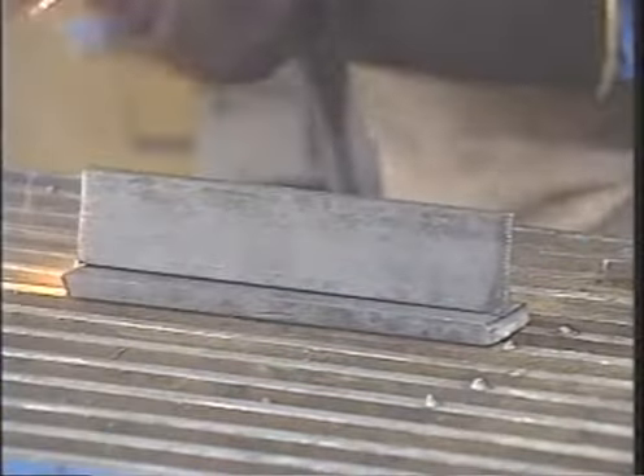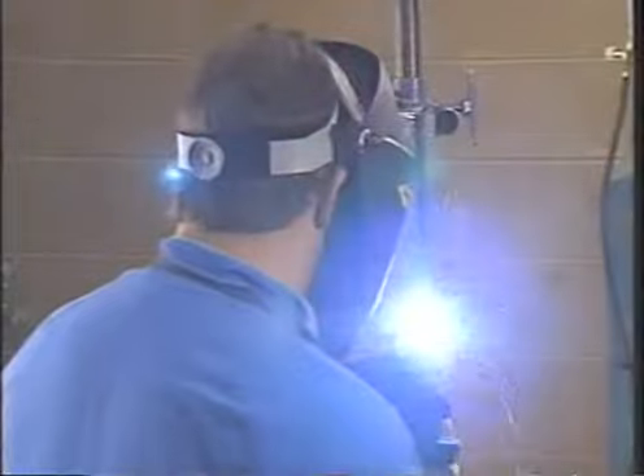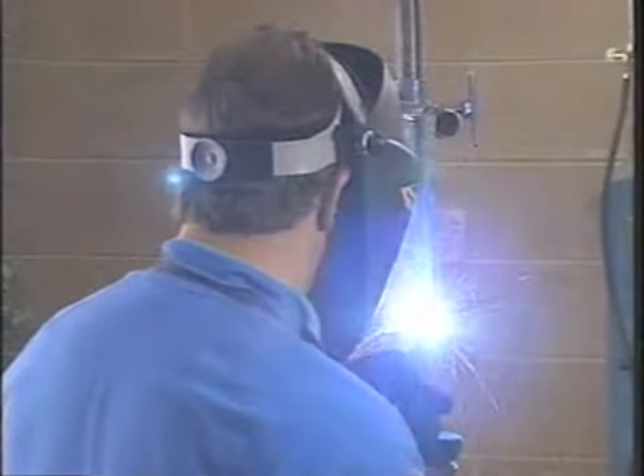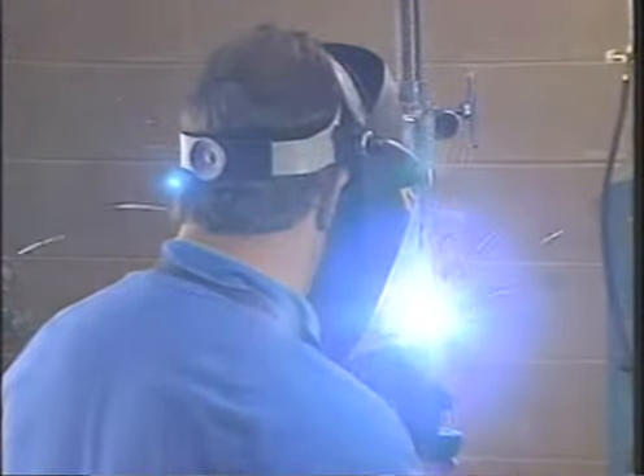To hold the plates in position, tack at either end. Then, using the short arc transfer method, commence welding at the bottom end of the welded joint. To ensure root penetration and a flat weld face, the welding gun should be moved in a triangular motion whilst moving up the weld joint.